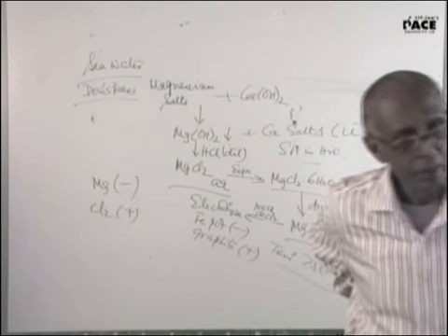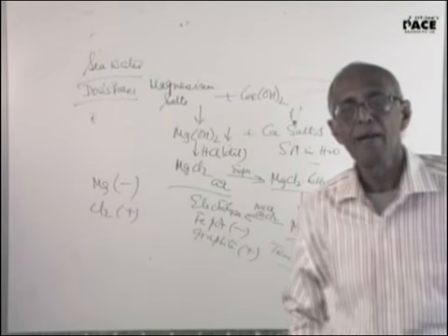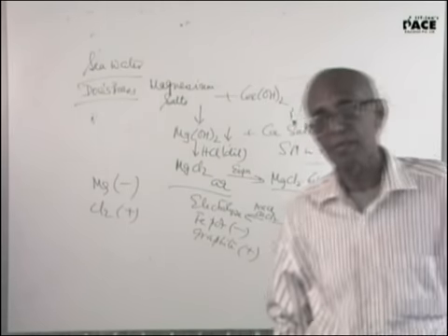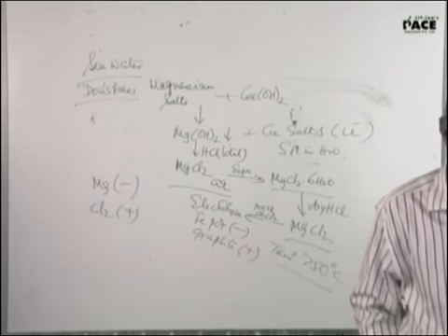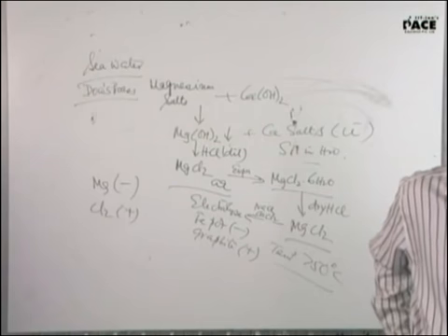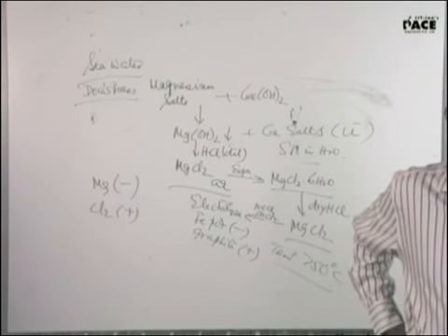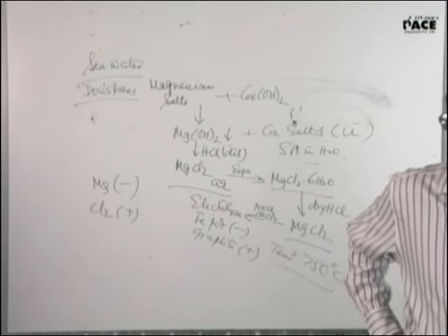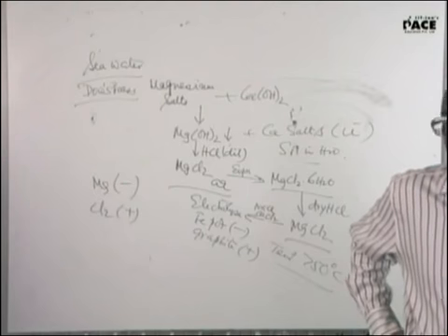Now I mix magnesium chloride with sodium chloride and calcium chloride, and the mixture melts at a lower temperature than magnesium chloride. So if I electrolyze at 750 degrees Celsius using iron as cathode and graphite as anode, then I get magnesium at the cathode and chlorine at the anode. And that is how magnesium can be prepared.